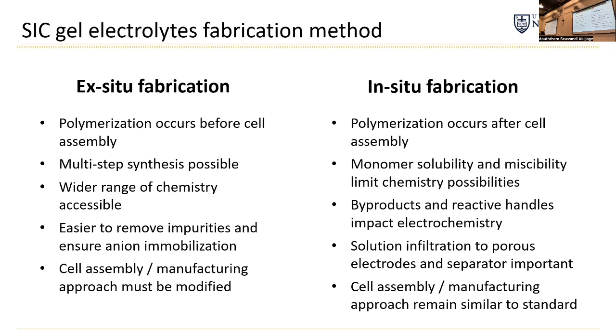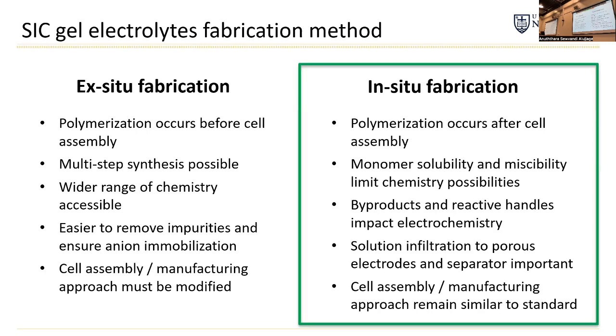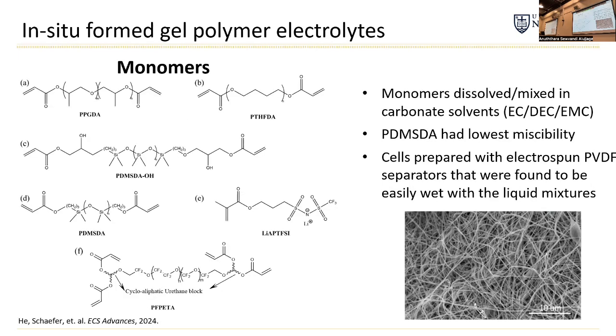And if you're doing reactions inside of the cell, there are reactive things in there, and this can impact your surface chemistry. The other big difference is that solution infiltration is super important. If you start adding things into your electrolyte, you change the viscosity, and this will change how the materials get into the porous electrodes or into the separator. But if you do this carefully, it's possible to keep your cell assembly and your manufacturing approaches very similar to current ones. So it could be the next step in reducing the amount of liquid inside of the cell and decreasing the plastic content. And so we started looking at this.